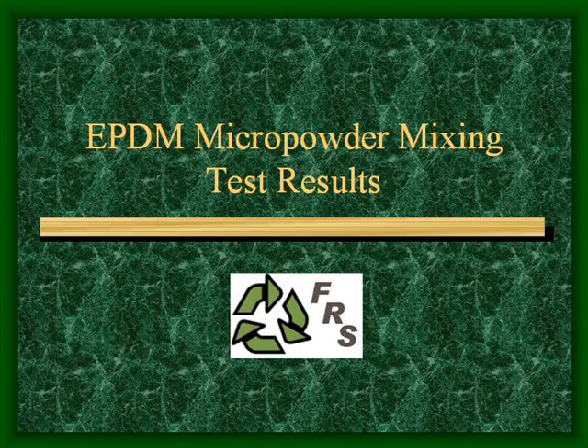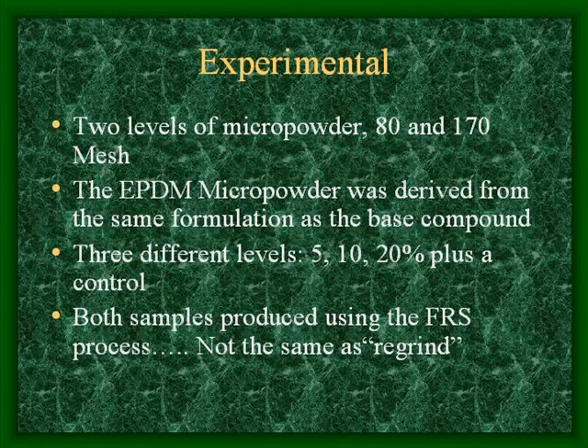These are the test results from the EPDM Mixing Experiment. We had two different levels of micropowder, 80 and 170 mesh. The micropowder was used at three different levels, and both samples are produced using the FRS process and are not the same as conventional regrind material, which would have tested completely differently.